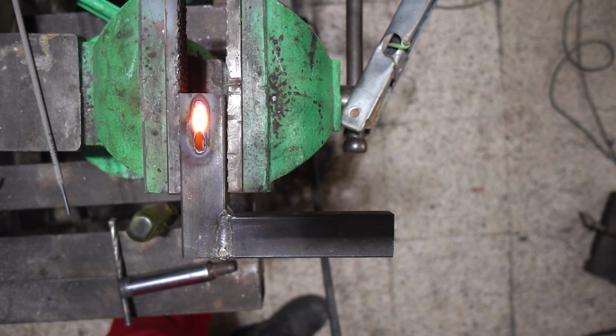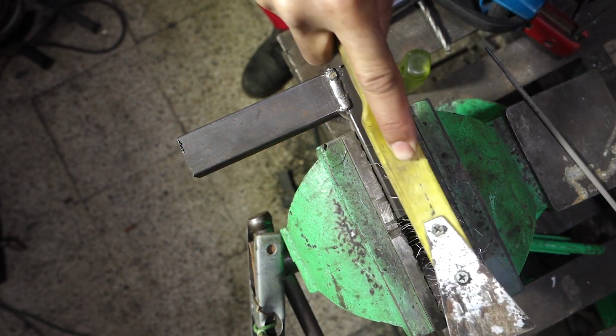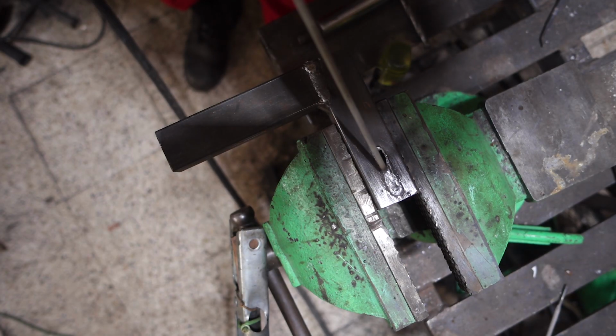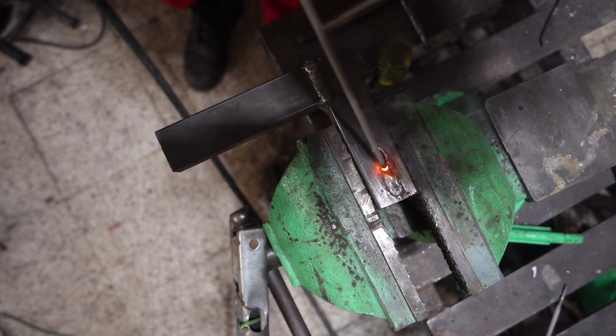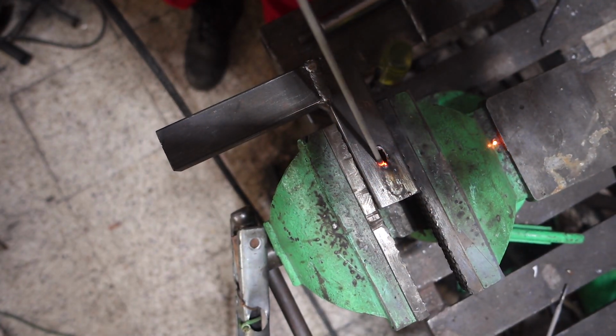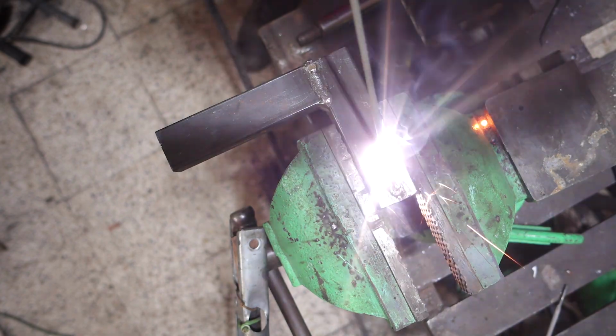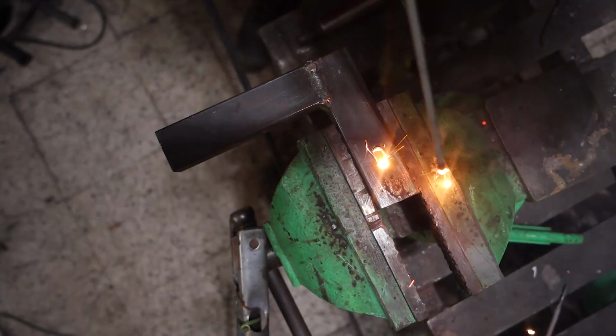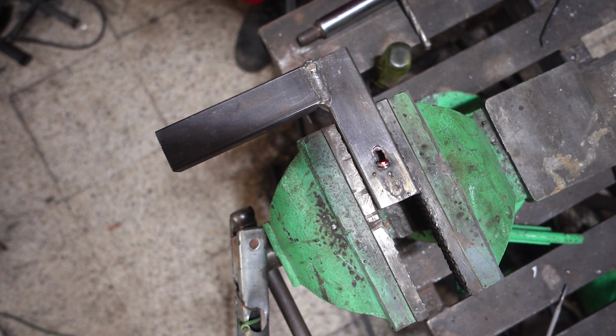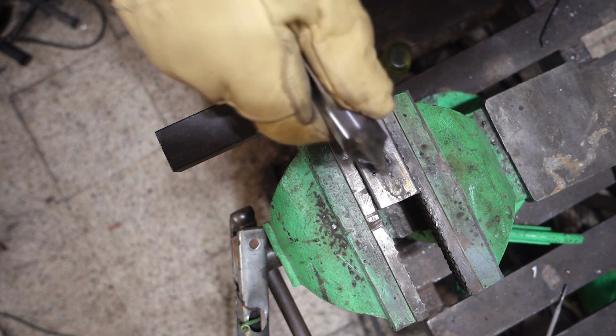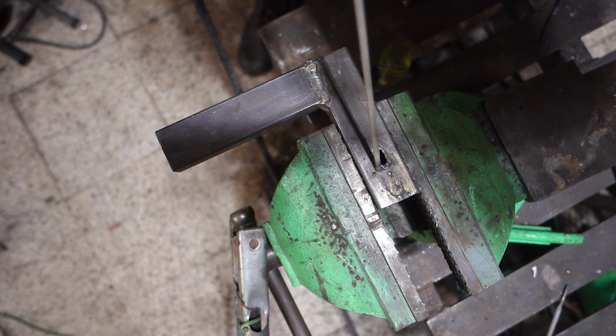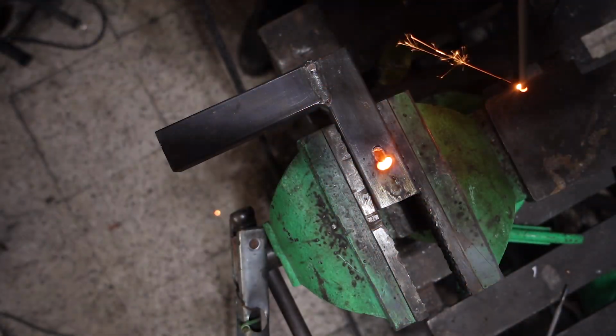Now we will learn how to correct when we burn a hole while we are welding. Be sure if you are welding thin steel, sooner or later this will happen. Start from one side and advance. I am trying here to make this side thicker so I can weld from it. Don't forget to clean if the area gets cold, or you will trap the slag inside the weld bead. When it became thicker to handle the heat of the weld, I continue.